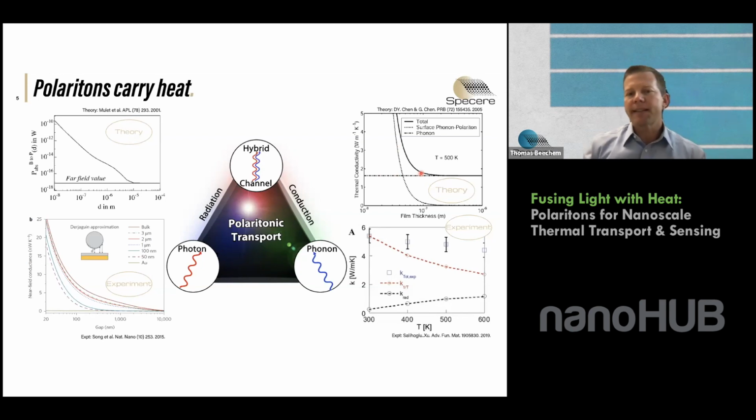And so as you get to these hundreds of nanometers levels, the phonon polariton's actually carrying more energy than the phonons themselves. And I just want to say up front that you do not need to shine light to get these polaritons to move in this conductive mode. Fluctuation, dissipation, and temperature gradients, I should say, rather than heat gradients, suffice to kick off these polaritons. And so this was a theory for quite some time.